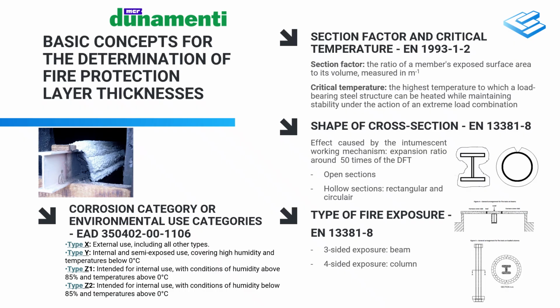The critical temperature is determined by a mechanical fire analysis, which specifies the maximum temperature to which a structural element can be heated up without losing its load-bearing capacity. The higher the critical temperature of the structural element, the thinner the additional thermal insulation layer required in the event of a fire. The next factor is the cross-sectional shape, which is defined in the testing standard, and at first glance this may not seem like a significant factor. But due to the heat-activated intumescent mechanism of the fire retardant paint, it becomes a key element.